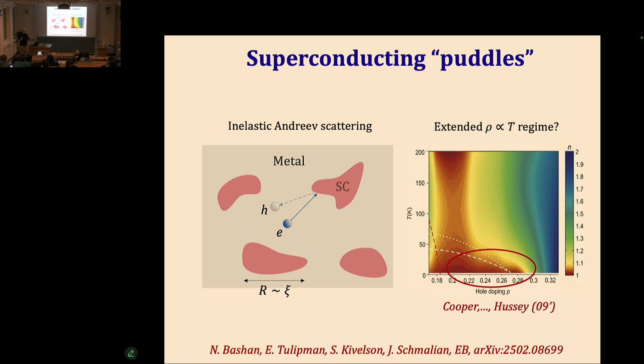It's basically on the verge of localization of the system. So it's when the system is so disordered that the normal metal is actually not a good metal anymore. Whereas in a D-wave superconductor, as we know, you'll start to destroy superconductivity already when the mean free path is of the order of the coherence length. So getting these puddles in a good metallic environment, you can only do that in a non-S-wave superconductor. Now the nature of the D-wave on every puddle, that's a different question. I sort of ignored it in this analysis, and we can talk about that. That actually has interesting effects by its own.